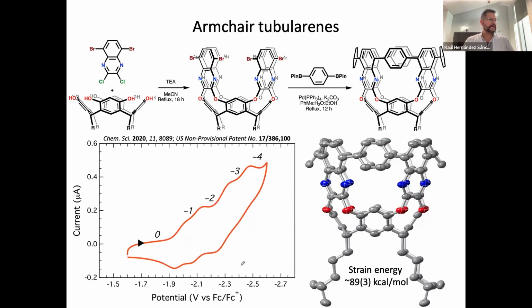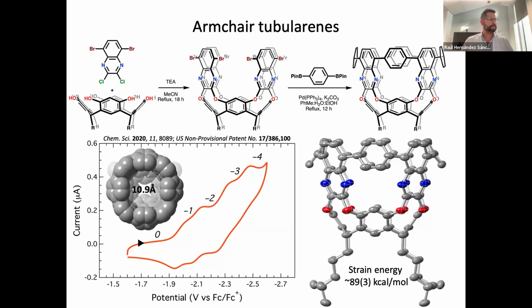Now, we investigated this species and realized that you can reduce it four times, or up to four times. It has an interior cavity shown there of slightly longer than a nanometer. And when we were getting this data, we were thinking, what can we use them for? So one of the things we envisioned was, well, these are nitrogen atoms shown right here. And if you hypothetically have acid around, you can potentially protonate this. And if you are lucky enough, you can potentially protonate it twice in an adjacent fashion to form these kinds of species. And if you can reduce it, as we proved the compound by itself, then you can potentially evolve H2, right? So that was the hypothesis.